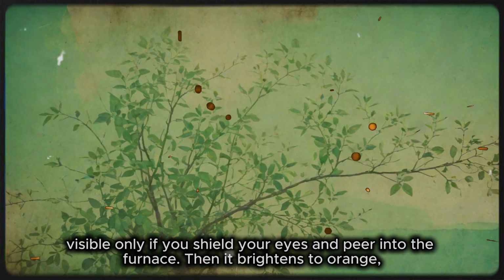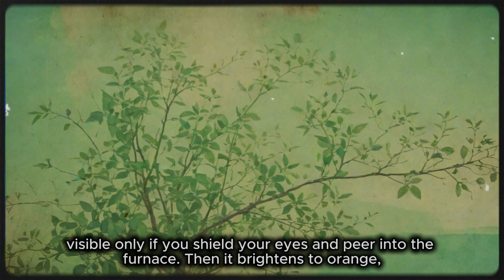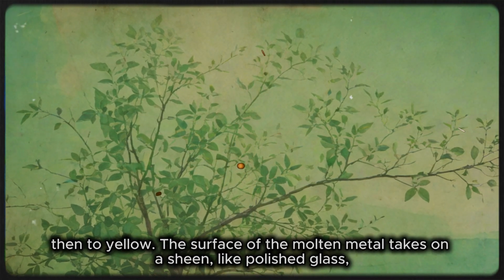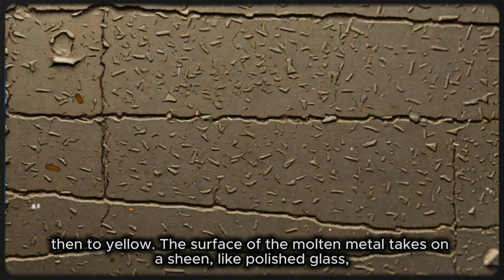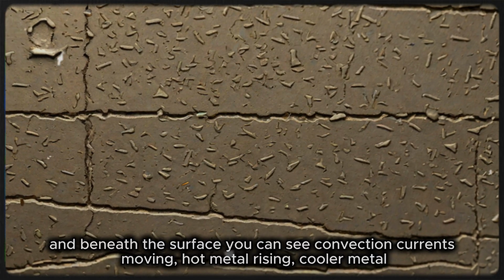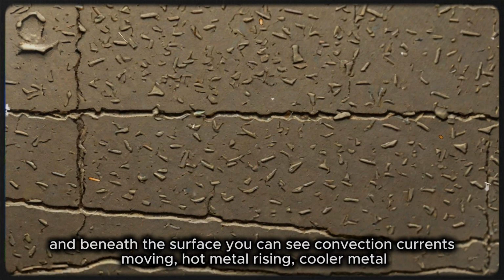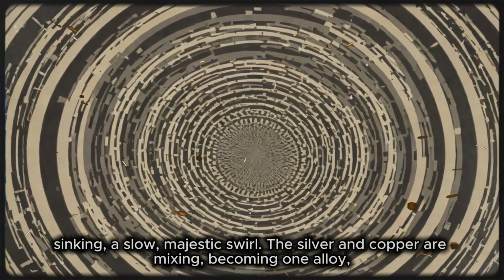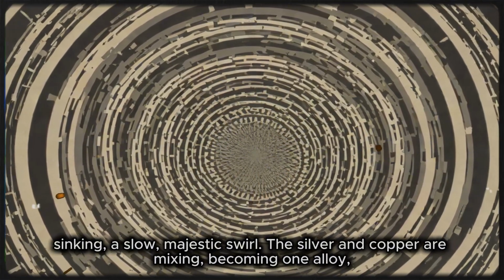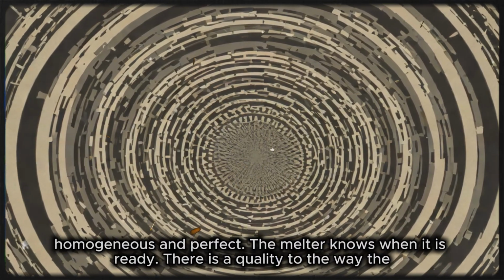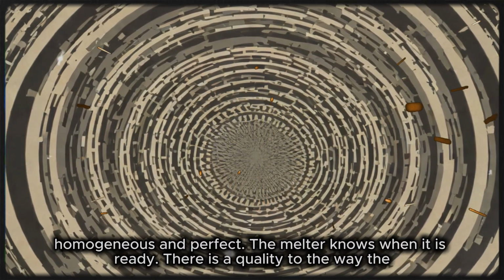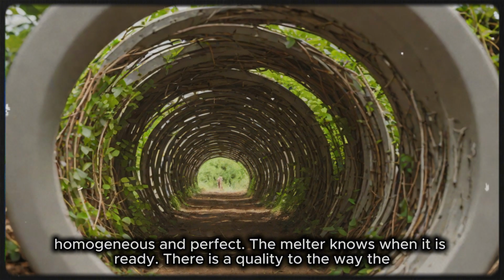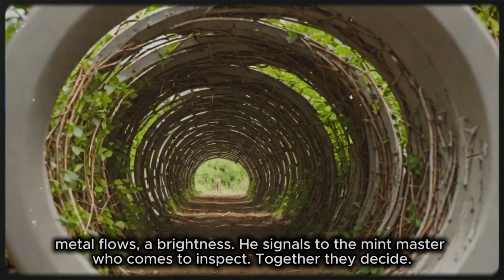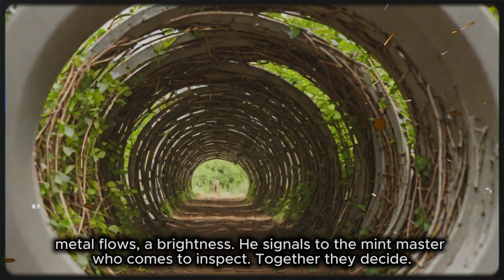The glow starts as a deep red, visible only if you shield your eyes and peer into the furnace. Then it brightens to orange, then to yellow. The surface of the molten metal takes on a sheen like polished glass, and beneath the surface you can see convection currents moving, hot metal rising, cooler metal sinking, a slow, majestic swirl. The silver and copper are mixing, becoming one alloy, homogeneous and perfect. The melter knows when it is ready. There is a quality to the way the metal flows, a brightness. He signals to the mint master who comes to inspect.